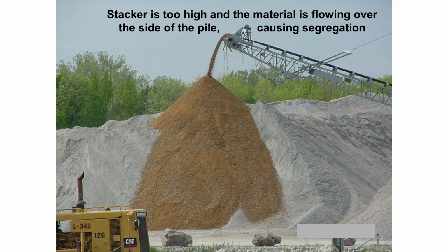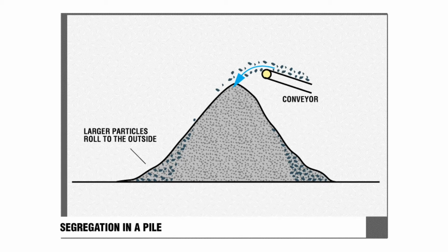We want to make sure we're not running that material over the side of a pile, because you can see in this shot right here that the coarse stuff's going to roll to the outside and the fine stuff's going to stay on the inside. And that's what it will look like in the stockpile. You can see the coarse stuff's all on the outside of the pile, and they call them center cone fines. That's what's on the center of that pile.